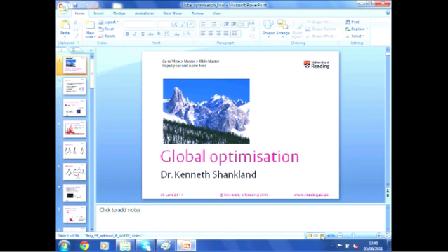Third one is if there is more ambiguity, for example, if you have an active pharmaceutical ingredient and maybe a solvated form, and you're not exactly sure what the solvate component is, then you can use maximum likelihood to effectively bar that contribution out, solve the substructure, and then do some different optimization to position the missing fragment. So there are various ways, it's certainly a tractable problem. And ultimately, you can always hit the chemist who gave you the wrong structure to begin with, and put the blame on them.